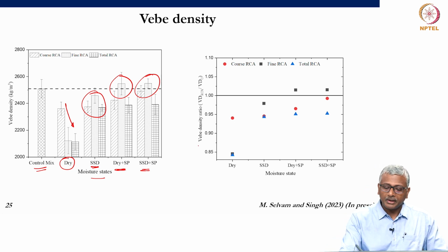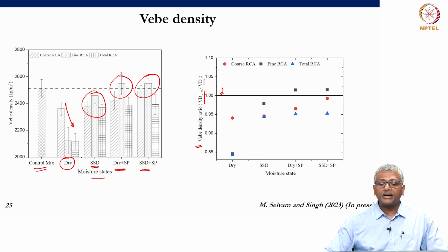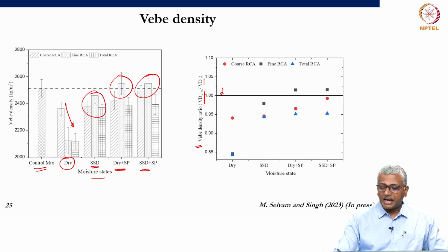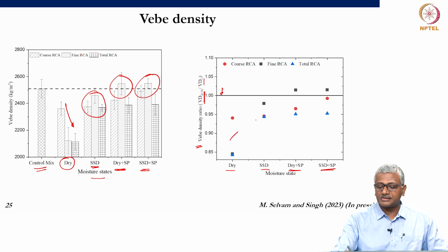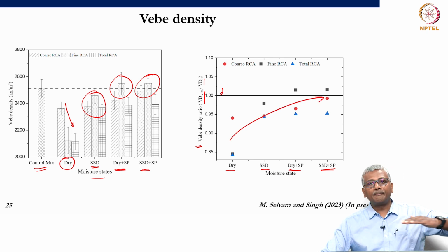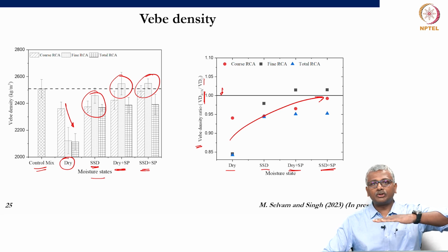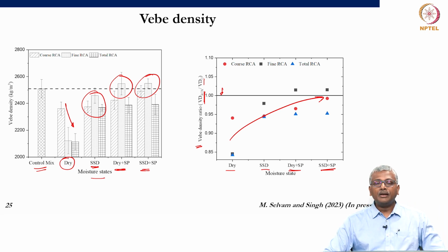Okay. So, again this is showing you the density ratio in terms of the concrete density with the recycled concrete aggregate and concrete density with the normal aggregate. So, of course, one indicates that it is equal to that of the normal aggregate. So, as I change from dry to SSD to dry plus superplasticizer and SSD plus superplasticizer, I am going closer and closer towards the density level which I can achieve with normal aggregate or natural aggregate. Okay. So, what it goes to show is compensation for the moisture absorption by making the aggregate saturated surface dry and use of superplasticizer together are now able to achieve recycled concrete characteristics that are equivalent to normal concrete.